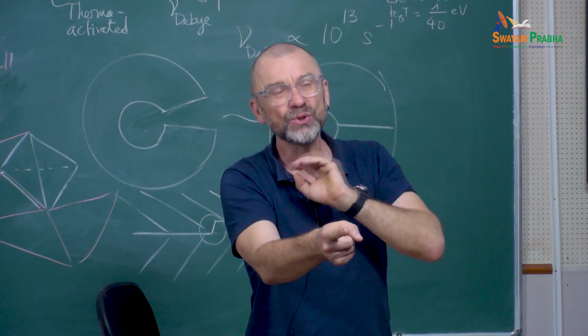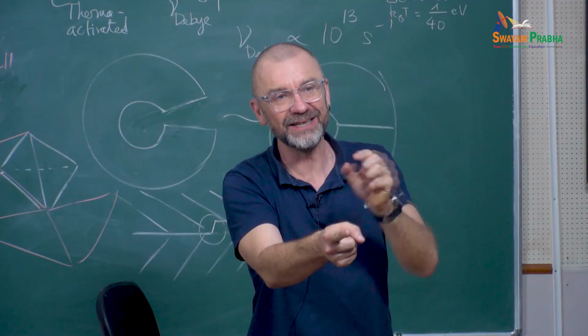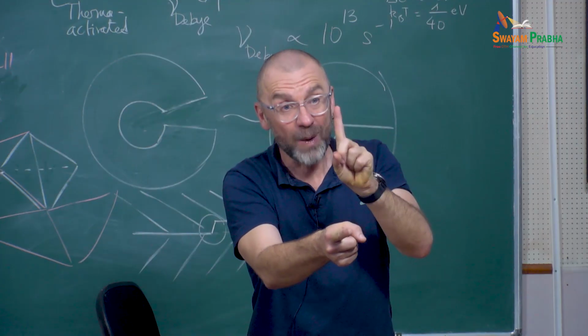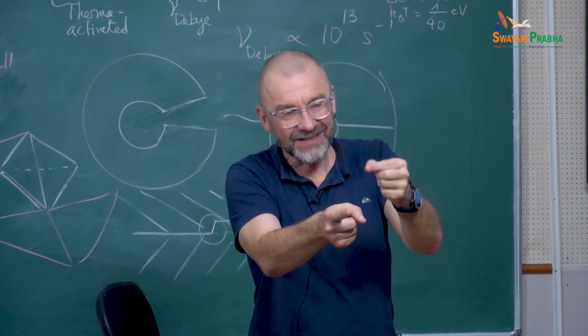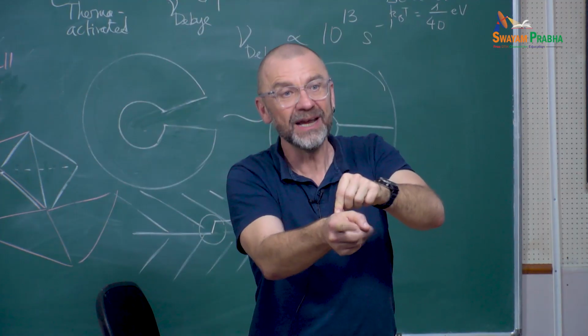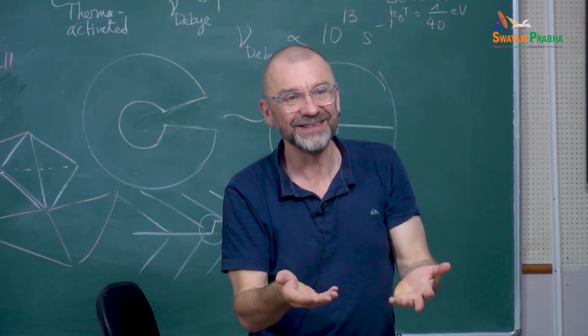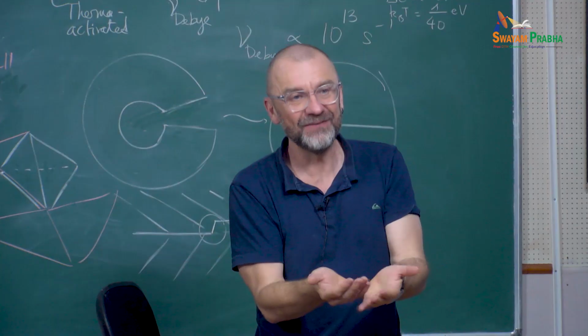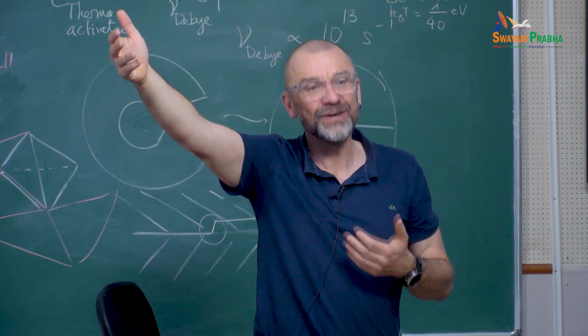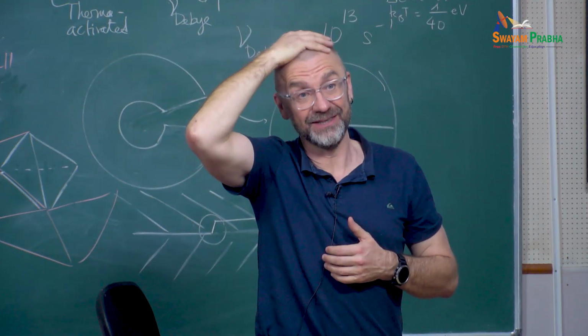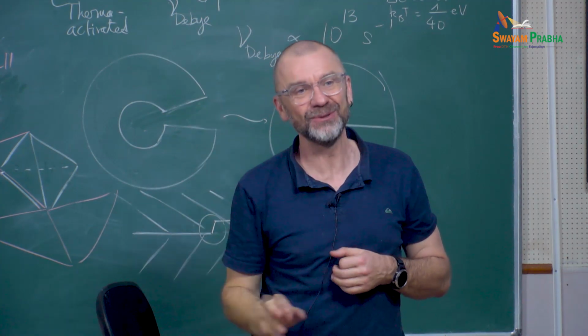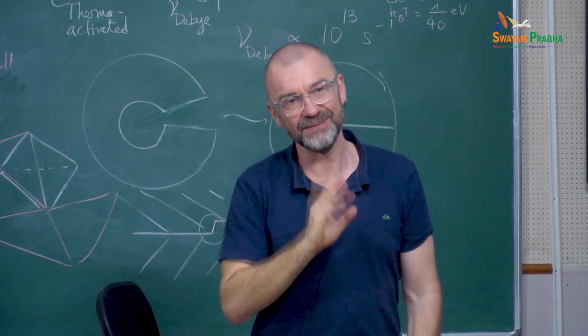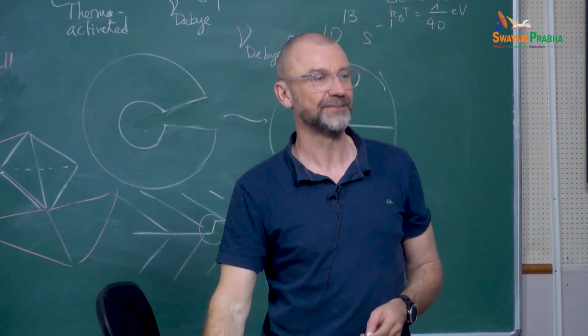I will be super saturated. So even just one dislocation. Even if that dislocation was able to be absorbed, I would overestimate the climb velocity because I'm overestimating the concentration of vacancies. Climb is extremely difficult to simulate even in simple systems at the atomic scale.